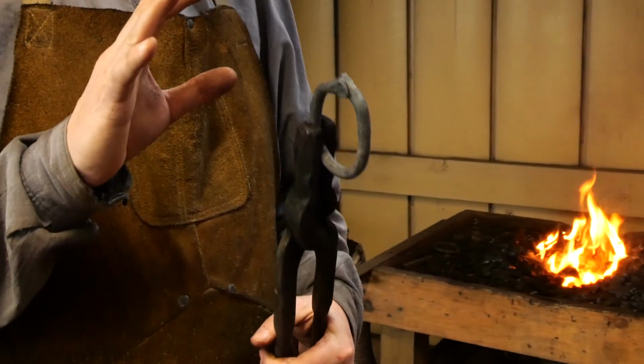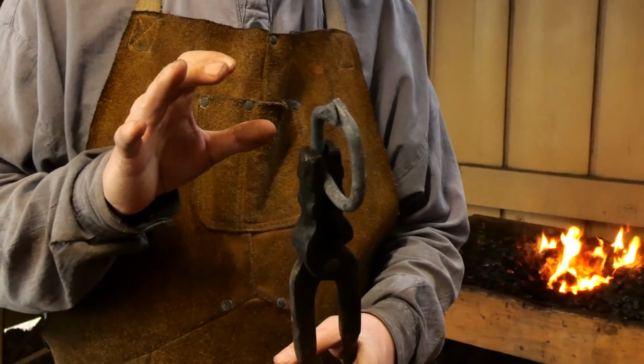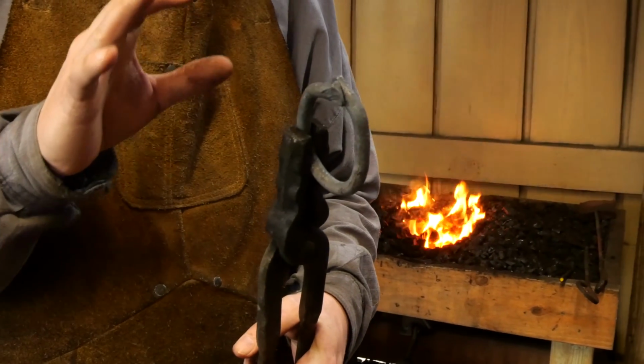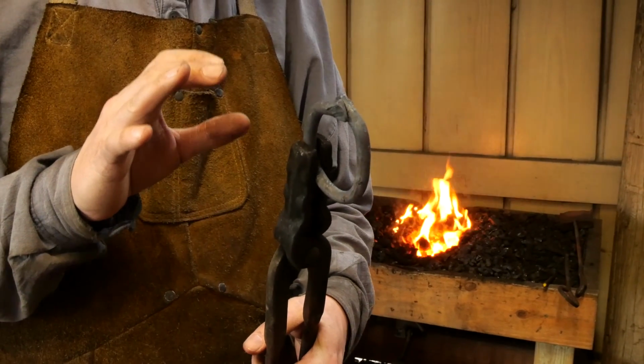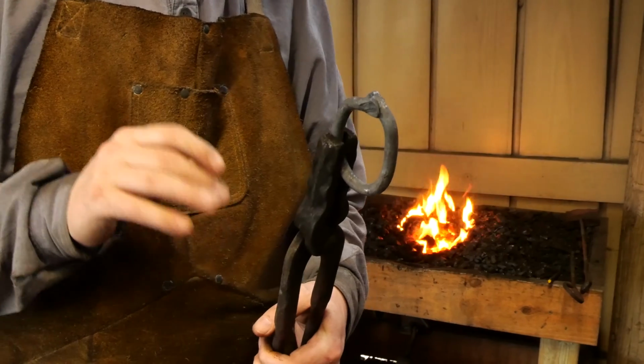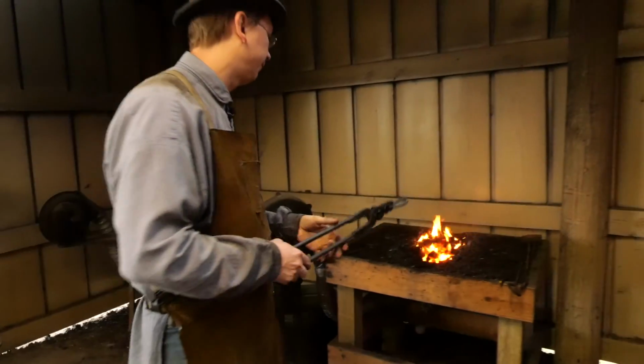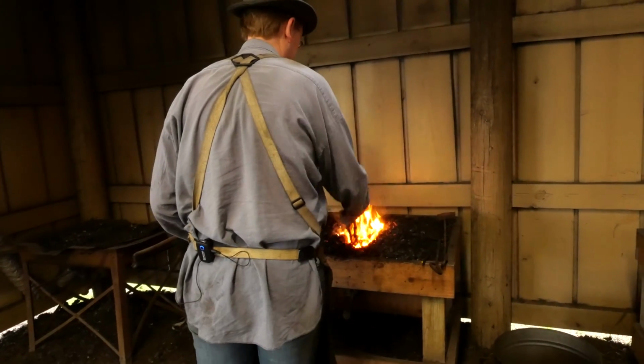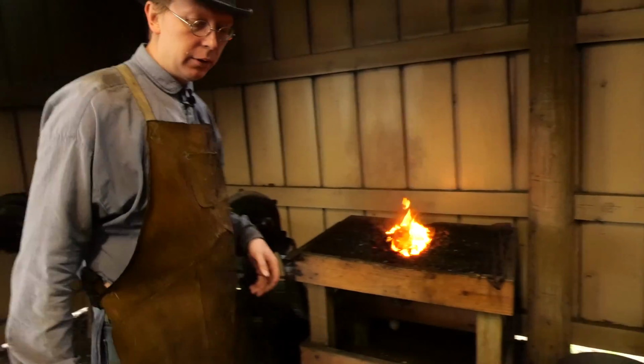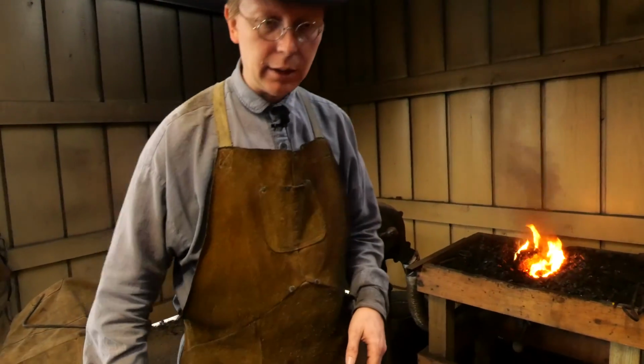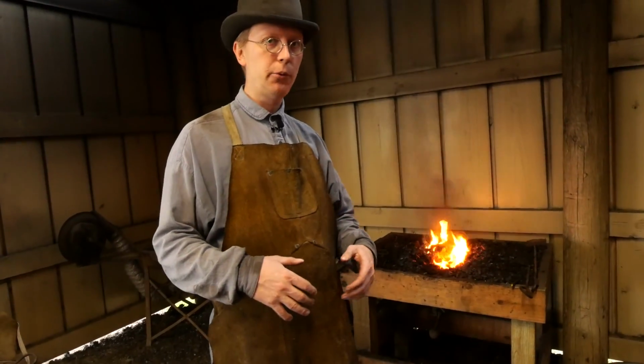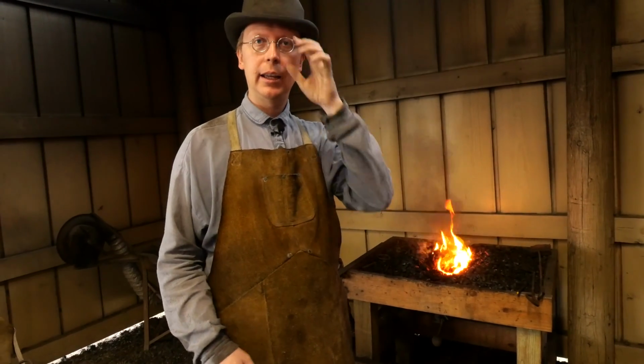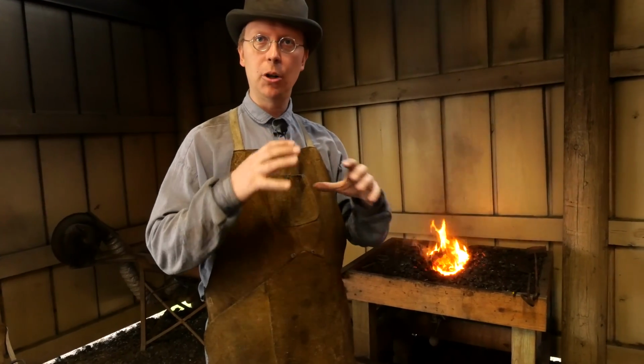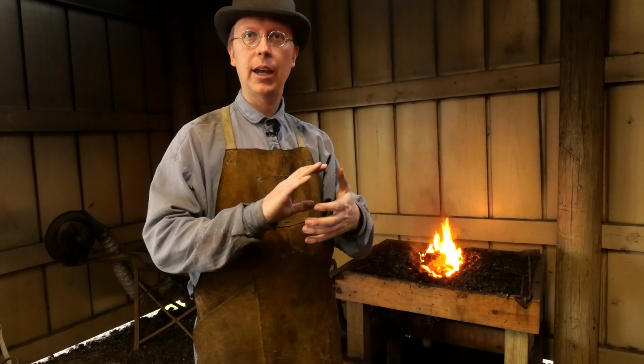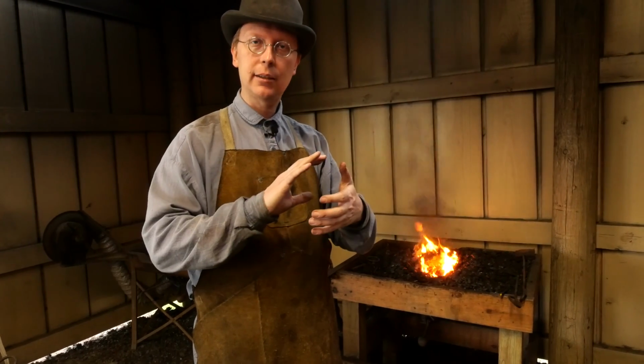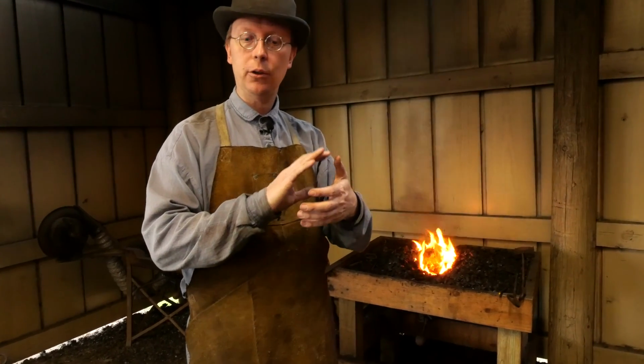All right, we've got our chain link ready to be welded up here. So we're gonna put this in the fire, start getting it hot, and let's talk a little bit about the forge welding process while this warms up. So the key to forge welding is really getting the steel hot enough that the surface of it starts getting a little molten-y. You hammer that together, and if you do that successfully, then when it cools down, you've got a single piece